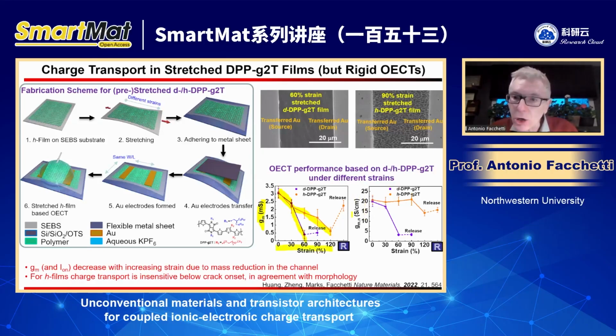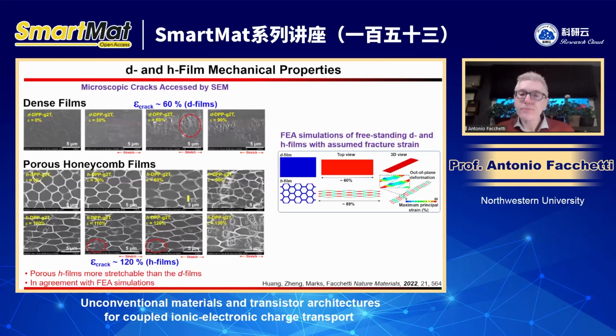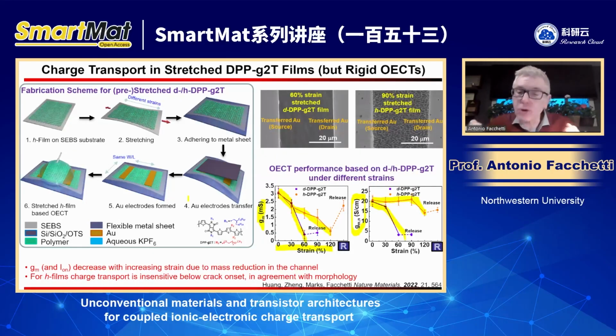But if you normalize the current, the transconductance, with the strain, it means you normalize for the mass of the material in the channel. Then you see here that it decreases a little bit, then it decreases a lot when you're at about 60% because it starts cracking the film. Instead, the honeycomb remains stable up to about 100%. Then at 120 it starts cracking. So the charge transport in the honeycomb film is insensitive to the stretching when the W/L remains stable.